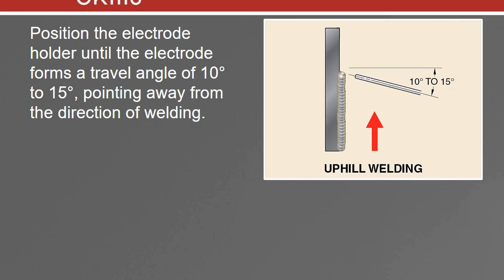Now, in uphill welding, you want to position the electrode holder until the electrode forms a travel angle of 10 to 15 degrees pointing away from the direction of welding. Now, I like to say about a 5-degree angle pushing up. One of the reasons is because you guys are learning how to weld right now. If you start on a 10 to 15-degree angle, by the time you get to the top of your weld, you've gone from a 10 or 15-degree angle to a 25 or 30-degree angle. If you start at about a 5-degree angle, naturally you're going to twist your wrist up, especially as a beginner, so by the time you get to the top, you're going to be at about a 15-degree travel angle.